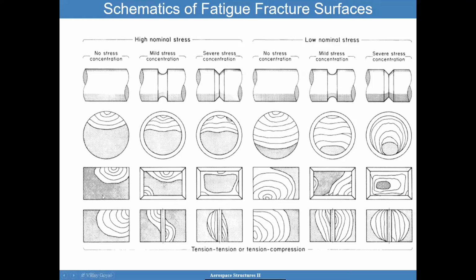If I look at rectangular samples, it's a very similar situation. Again, no stress concentration, high nominal stress. You'll start seeing some initiation points here. It could look like that. It could look like this. You could have a situation where, if you have this type of high nominal stress condition, the crack could propagate in a different location. It could initiate at different points and then leave you with some amount of fracturing left.